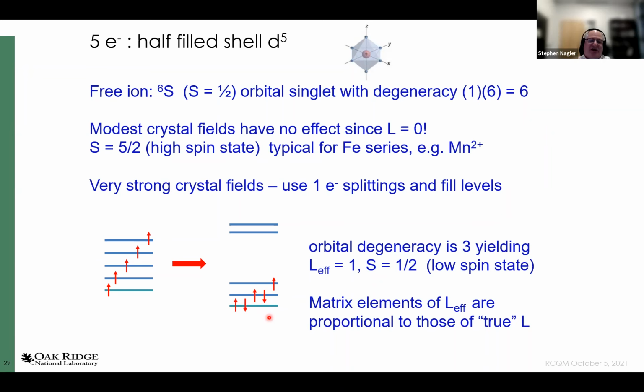And what I find is with a T2g type triple orbital level and 5 electrons, I have a spin of 1/2. These guys cancel out. And because I can put that spin of 1/2 in any of these levels, I have effectively threefold degeneracy, L equals 1. So I'm left with spin 1/2, L effective equals 1. And this S equals 5 halves we call the high spin state here, S equals 1/2 we call the low spin state. Obvious nomenclature.